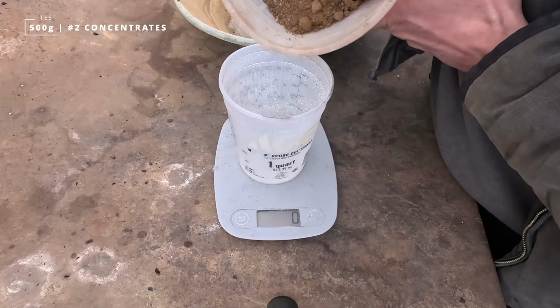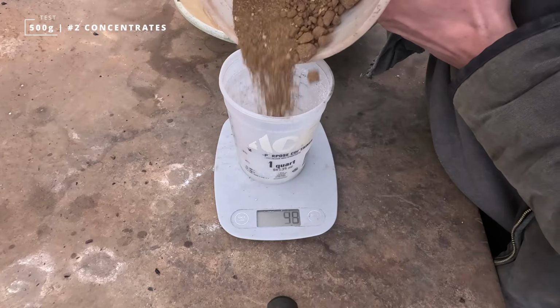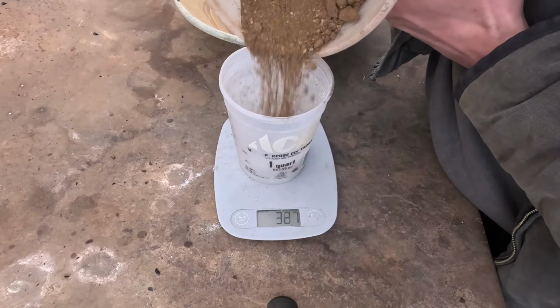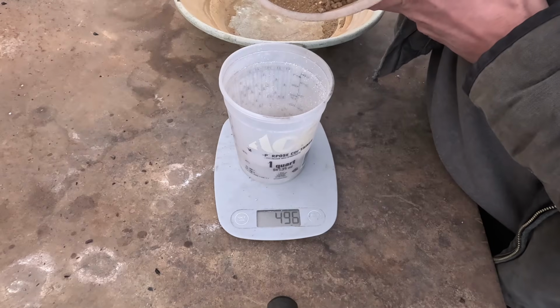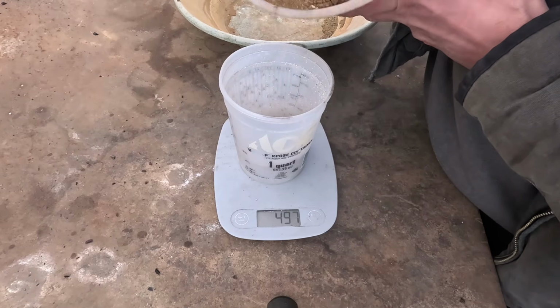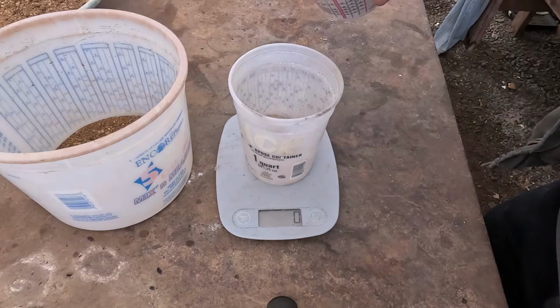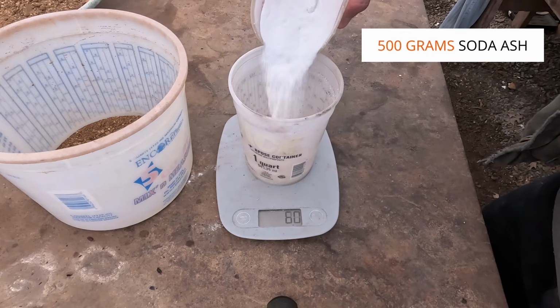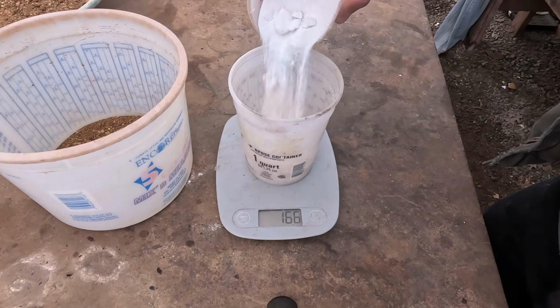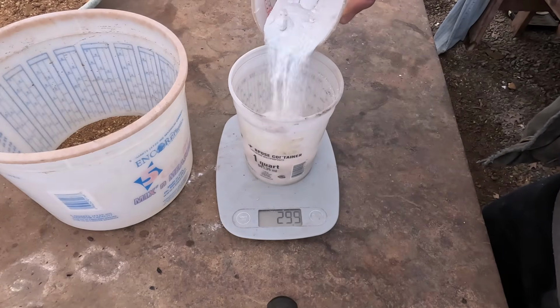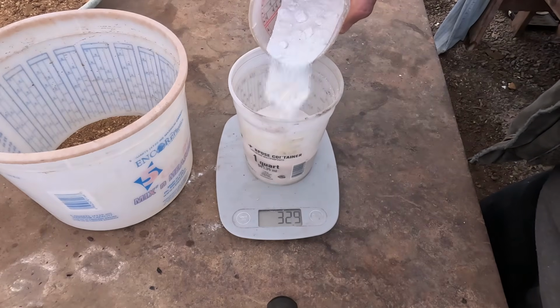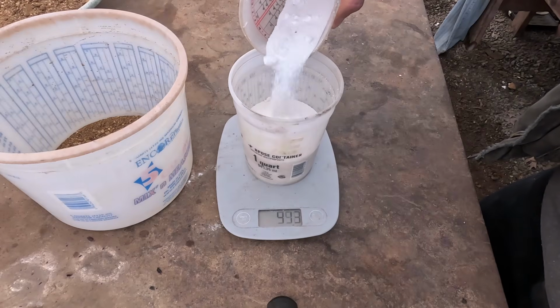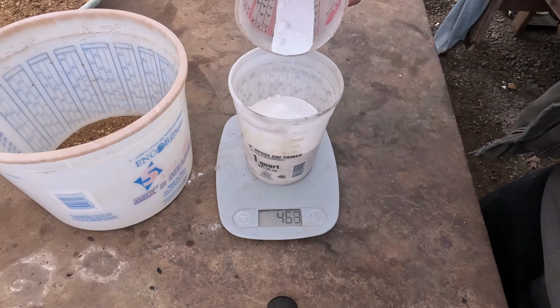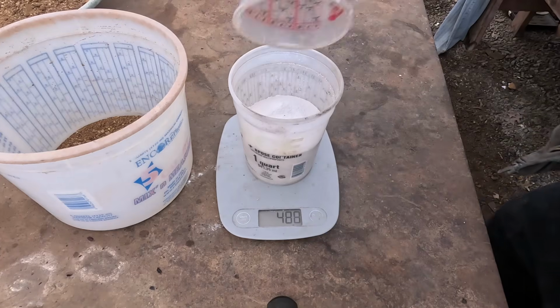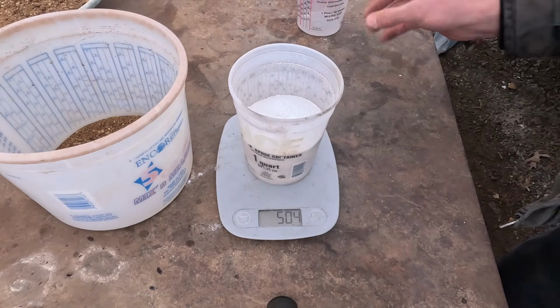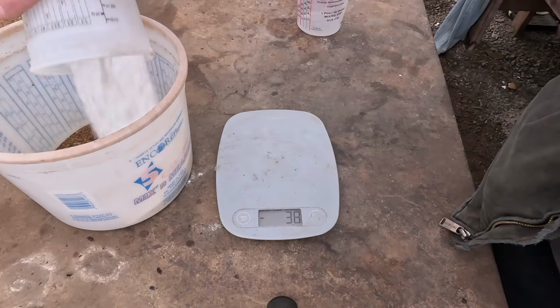So let's measure out 500 grams. Seems like a pretty good number. So there's 500 grams of concentrates. Now I'm gonna mix 500 grams of soda ash, and this is going to make a basic slag that will help absorb all the iron sulfide that we're gonna make. So 1 part cons, 1 part soda ash. Oh, it's gonna be perfect. Almost. There we go. Pour that in with our cons.